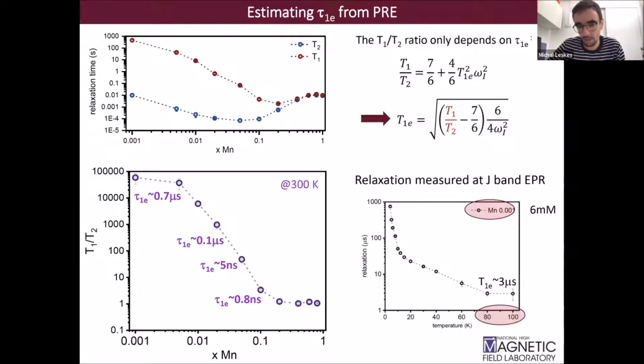And so we try to do EPR relaxation measurements. For that, we went to high field in Florida, at Tallahassee, and measured the electron relaxation time up to a temperature of 100 Kelvin. Above that, the relaxation time becomes too short to be able to measure. And we obtained at this 100 Kelvin, for one of the lowest manganese contents, a relaxation time of about 3 microseconds, which if we extrapolate to 300 Kelvin, shows us that we are at least in the right order of magnitude to estimate electron relaxation times just from the ratio of T1 over T2.